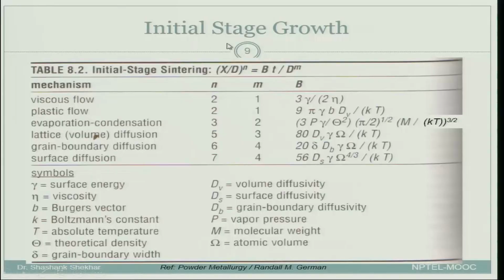If you were to look at the equation, it will look like this. In the initial stage growth, you will have x over d, x is the neck size, d is the diameter, and b is some constant which carries the process parameter. It also carries some of the material characteristics, and it will be given depending on what is the mechanism. So, the different mechanisms are described over here, and for them the n, which is the exponential factor over here, and m, which is the exponential factor over here, are given. So, for different mechanisms like viscous flow, plastic flow, evaporation, condensation, lattice diffusion, grain boundary diffusion, and so on, it is given over here along with definition of these different properties.